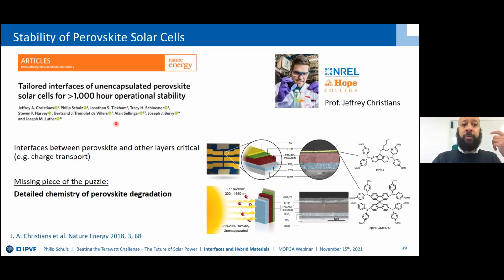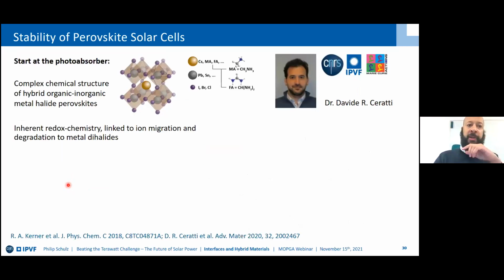And we were able to make solar cells without any protection that worked for 1,000 hours under operational conditions. And this was really new. If you would have asked us 2 years before, we were not even half as optimistic to get to something like this. However, what is really missing in order to finalize this kind of research is a detailed view on the chemistry of the perovskite degradation. So yes, we pull all these different levers and turn the knobs, but can we do it in a more targeted way? And therefore, we need to explore the material properties.